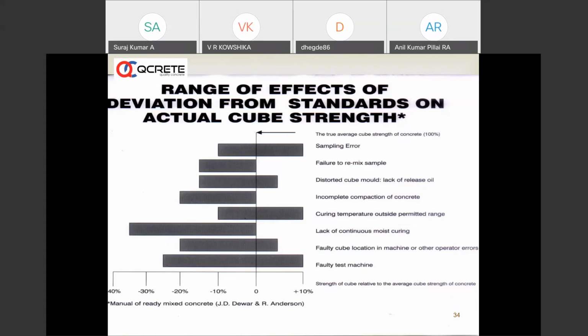Then after curing, if the machine operator doesn't know how to keep the cube in the center of the machine and crush it properly, then it will lead to a big negative impact. Faulty testing machine, uncalibrated testing machine, all will have a negative impact on the cube strength. We many times hear the strengths are varying, this kind of question. The answer is that if we don't do all these aspects right, sampling, remixing, if your cube molds are not all right, compaction is not done right, curing temperature, many of the sites we take care of everything.